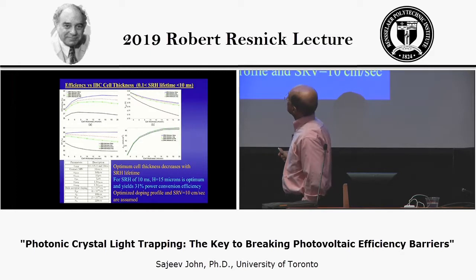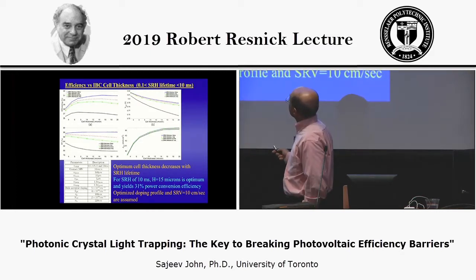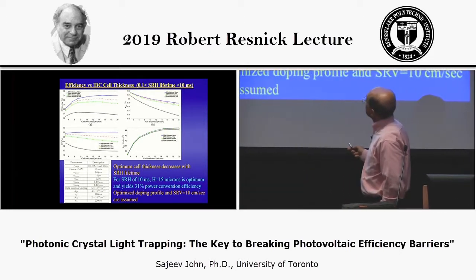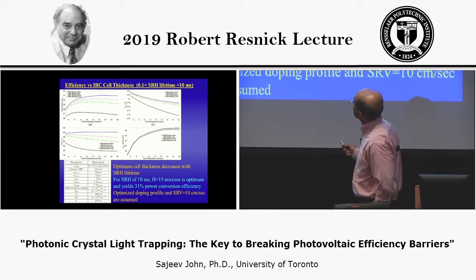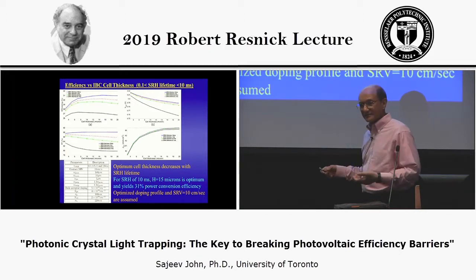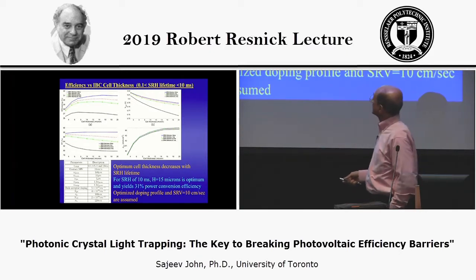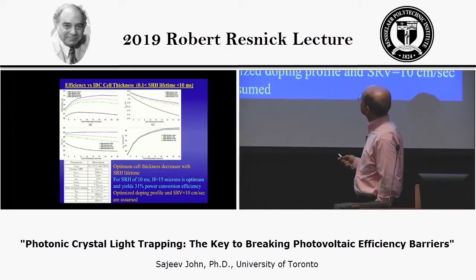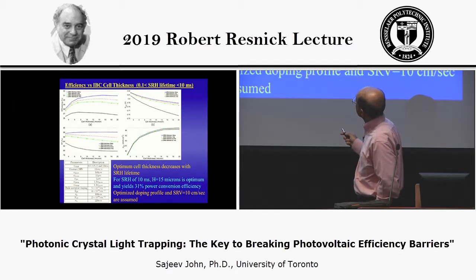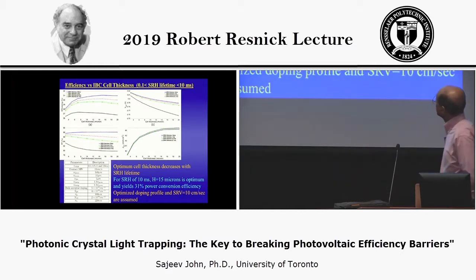And we do it for several different cases, ranging from the black curve, which assumes a Shockley-Read-Hall lifetime of, I think, 0.1 milliseconds. So that means there are a lot of defects in the structure, and there's recombination taking place at defects, up to the state-of-the-art value of 10 milliseconds, which is the blue curve. And here is where we find the optimum: a 15 micron cell would actually achieve an efficiency of about 31%.